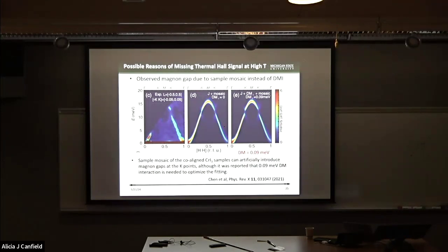and also in the previous PRX paper, all the measurements were done on co-aligned chromium triiodide samples. By the way, the samples were grown using a chemical vapor transport technique. And if you are familiar with such a technique, usually the samples that you can grow are very, very small. Therefore, you need to co-align a huge amount of samples for the inelastic neutron scattering experiments. Okay, so anyway, in this more recent inelastic neutron scattering experiment, they co-aligned the samples with a much smaller sample